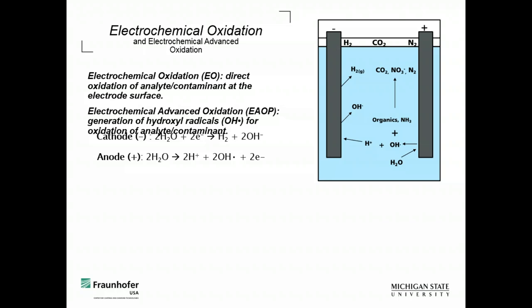In our space, a high voltage, high current is maybe 5, 10, 15 volts, and then maybe, depending on the size of the electrodes, 5 to 10 amps. We're talking anywhere from 10 to 100, 150 milliamps per centimeter squared is where we're actually operating here. But nonetheless, I just have organics here.